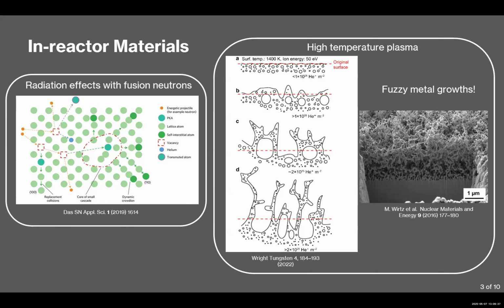So what can happen is the plasma itself, which is typically hydrogen or helium. Helium is the waste from the fusion process. Helium can go into the material, and at high temperatures it can form these bubbles. In this case in tungsten, which is one of the candidate materials for the plasma-facing components. It can form these bubbles which can then grow and rupture, and they make this fuzzy stuff on the surface, which is not great because you don't want little bits to break off and start whizzing around inside your plasma. That will waste a lot of energy.